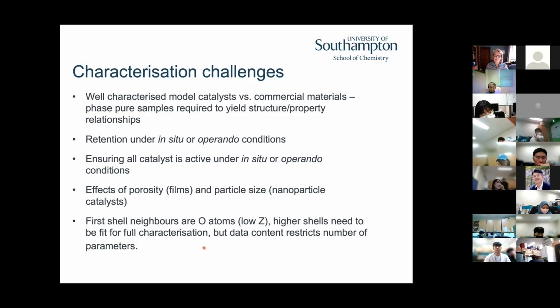Finally, when we get onto these oxide materials, we're worried about oxygen as our first shell neighbor. It's low Z. We saw that the spectra are going to decay very quickly as we go out in energy space. So it's tempting to not bother to collect higher k-space data. And that's always a mistake because it makes it more difficult to normalize your spectra and subtract the background. But it also means you're not helping yourself when it comes to calculating the spectra for higher shells. You need a bigger data range if you want to be able to have more parameters to fit. So make sure that you're paying attention to each of those aspects when using X-ray absorption spectroscopy.